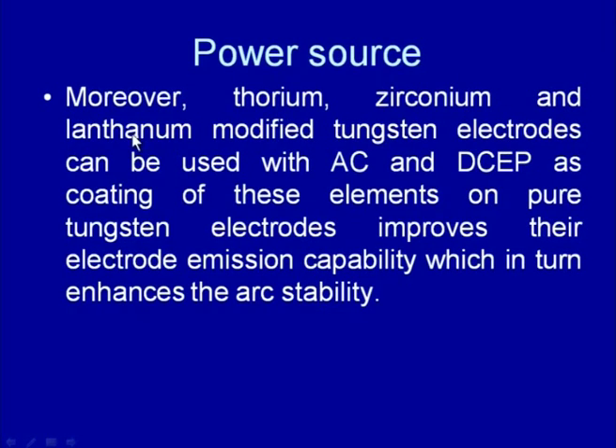And this easy release of the electrons helps these electrodes work very effectively, especially from the arc stability point of view. So, when the tungsten electrode is modified with thorium, zirconium and lanthanum, it can be effectively used with AC and DC EP, where the electrode is made positive. So, the base metal is expected to release the electrons. Under these conditions, these coatings on the electrode improve the electron emitting capability, which in turn enhances the arc stability. When this happens, the electrode life is improved significantly, and therefore, coated electrodes are preferred for the conditions where AC or DC EP is used.